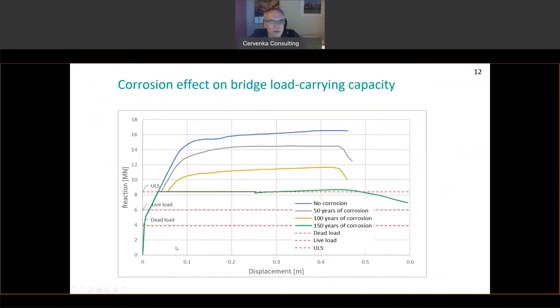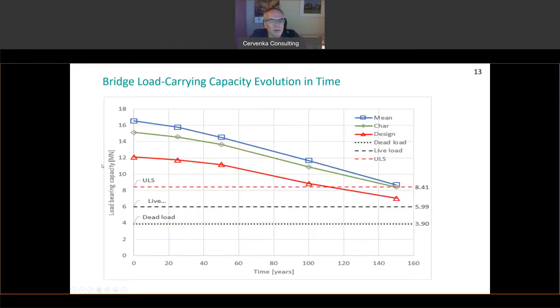So how do we apply this for structural assessment? At various times during this time-dependent analysis, we can perform a virtual load test of the structure — applying the design load combination and loading the structure up to failure — and then check what the safety margin is. The blue line shows the load carrying capacity of the original bridge without any corrosion, and then we have results from 50, 100, and 150 years. We compare the obtained loads with respect to dead load, live load, or ULS, which means the design load combination. To make a safety evaluation, we take into account some probabilities for failure and variability indices based on the codes.